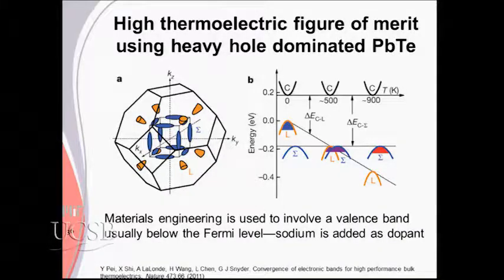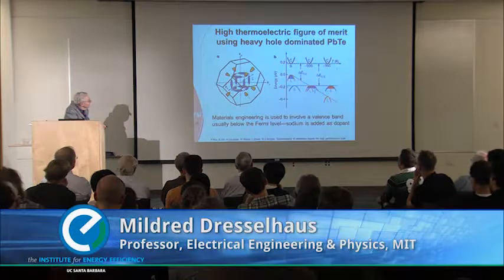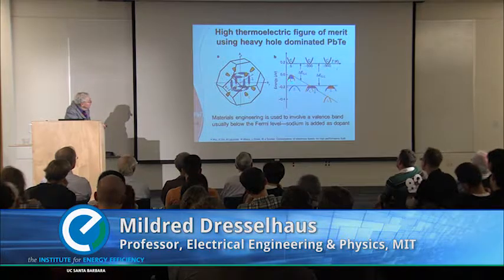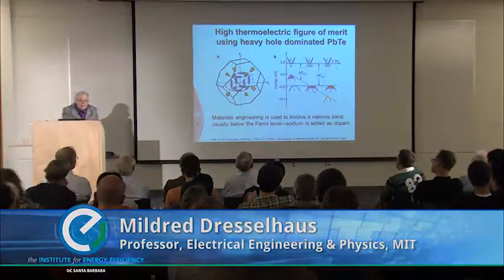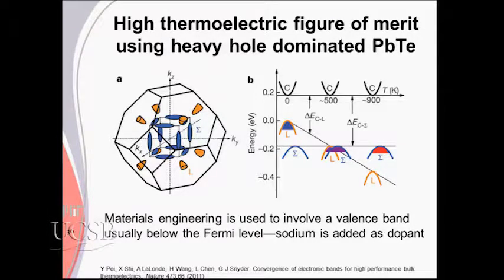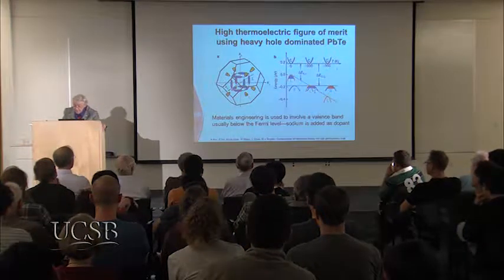And so another thing is looking around for materials with interesting properties. So lead telluride is an interesting one. Normally we think of the small band gap that we have, there's an L point band gap, and here's the L point band gap. But there's another band that has heavy mass carriers that if they could be included would be very good for making a P-type thermoelectric. So we have to have the right kind of dopant that would move this band up so the Fermi level would cross it. And that has been accomplished by a number of people. And this is one, Xun Shi is here, and Jeff Snyder is, some people might recognize them.